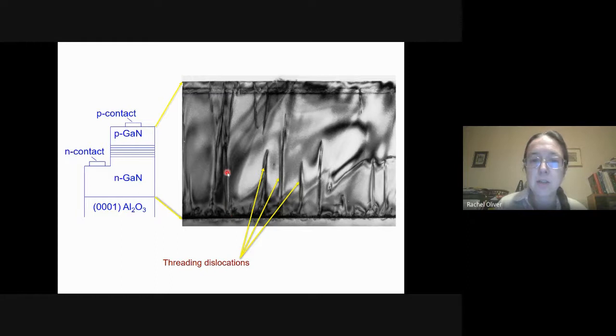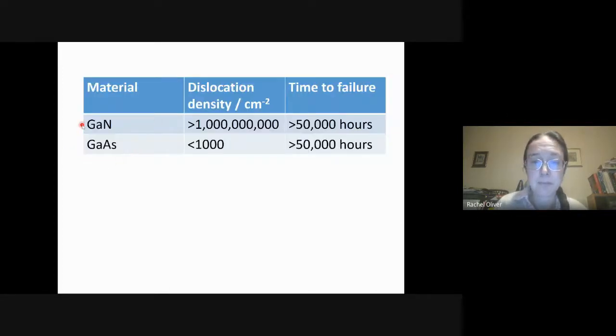And then those dislocations thread, we say they're threading dislocations, all the way up through the material, and they cross through the active region. Now, particularly in the early gallium nitride LEDs, even commercial devices had a density of dislocations per unit area of about a billion per centimeter squared. That's in contrast to materials like gallium arsenide, which are used for making infrared LEDs, and similarly the gallium arsenide, gallium phosphide family of materials, which are used for making red LEDs as well, where the dislocation densities would typically be around 1,000 per centimeter squared or less.